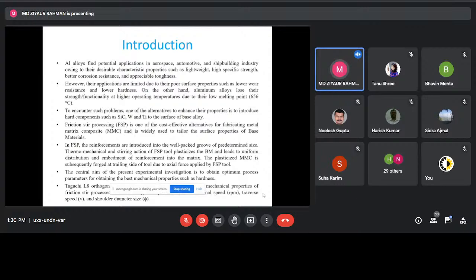Thermomechanical and stirring action of the FSP tool plasticizes the base metal and leads to uniform distribution and embedment of reinforcement into the matrix. The plasticized metal matrix composite is subsequently forged at the trailing side of the tool due to the axial force applied by the tool. The central aim of this study